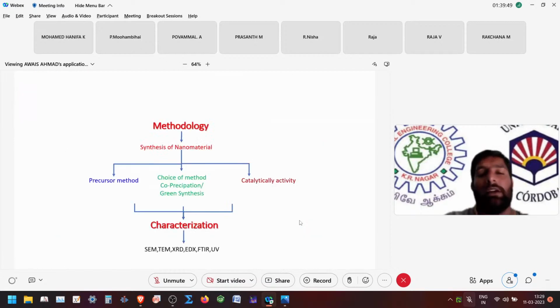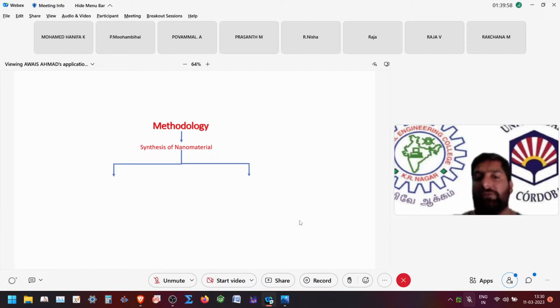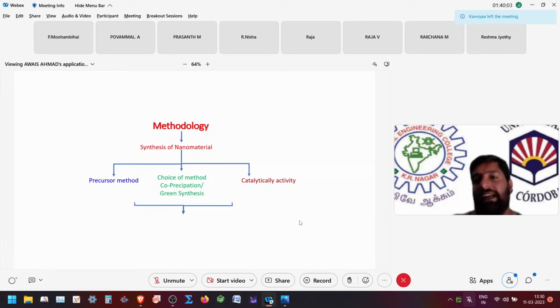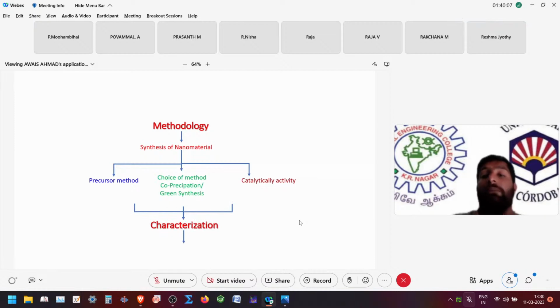So mainly with the methodology, what you students are going to do is, first of all, synthesize your material, and you have to choose your precursor and your choice of method. And then you have to decide which catalytic activity you are going to perform. And there are a number of characterization techniques which tell you about the nanomaterial's feasibility, whether it formed or it didn't form, which are SEM, TEM, XRD, EDS, FTIR, and UV.